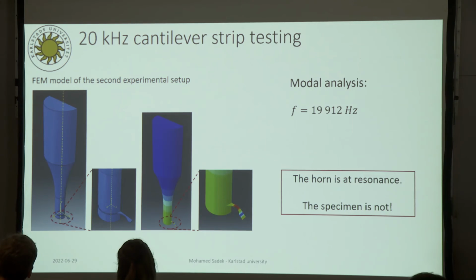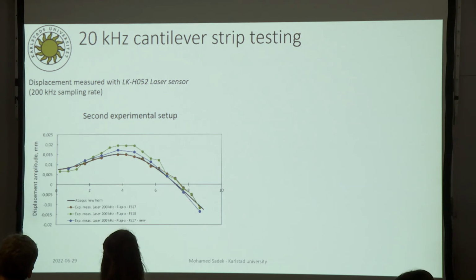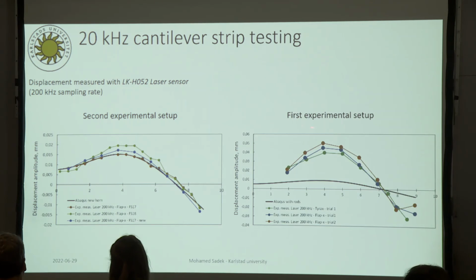Modal analysis shows a correct frequency and the same as before. The horn is at resonance, the specimen is not, it follows. And with this new setup, all of a sudden we get a very good agreement with the FEM model. So we do not get the discrepancies that we saw earlier from the first setup. That means that these modes that we think are coming in are not coming in when using the new horn. When using the new horn, the displacement amplitude is according to the FEM model.